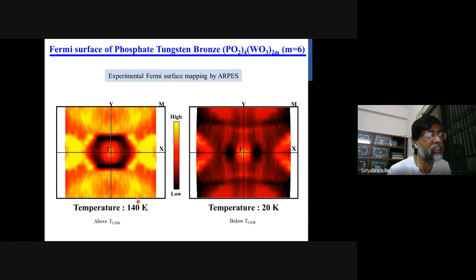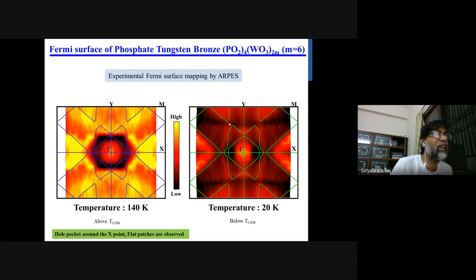140 Kelvin is above the CDW temperature, and 20 Kelvin is lower than the lower anomaly temperature. You can see there are differences in the intensity between the two Fermi surfaces. If I take this gamma point as a normalization factor, then both are overlapped with the two-dimensional Fermi surface calculation, and it matches quite well.